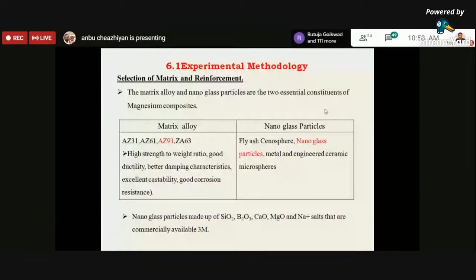Here are the chemical constituents of nano glass particles: SiO2, B2O3, calcium oxide, magnesium oxide, and Na, commercially available from 3M Technologies. This is what we have used. AZ91D is used as the matrix material. These are the chemical compositions: AZ91, aluminum 8.3%, manganese 0.13%, zinc 0.35%, and we have the XRD images of that.